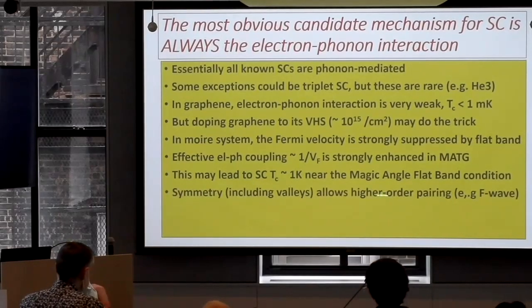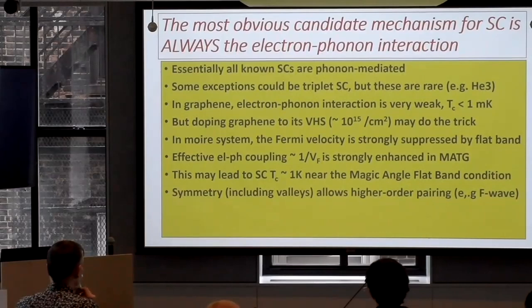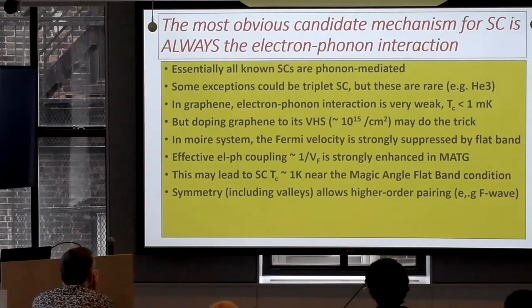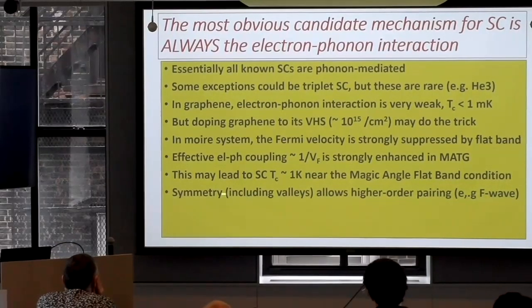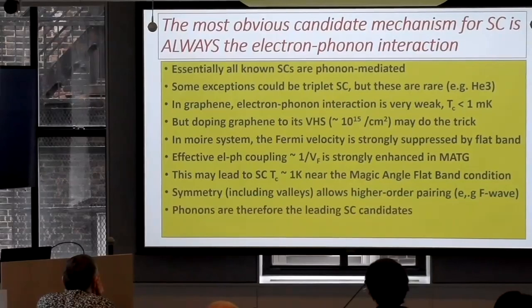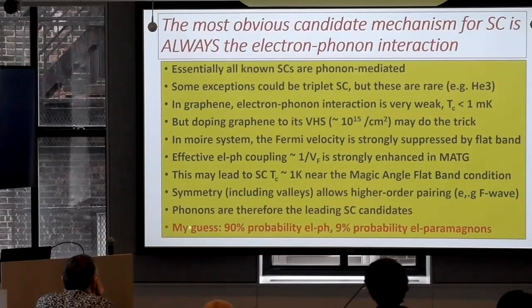Now, since you have symmetry, including valleys, you can have higher order pairing. Normally, electron-phonon interactions just give s-wave. But here, as I'll show you, there could be degeneracy between s-wave and f-wave. So the original argument was you cannot get higher order superconductivity, but now we know that that happens. So it's a candidate, and this question came up.